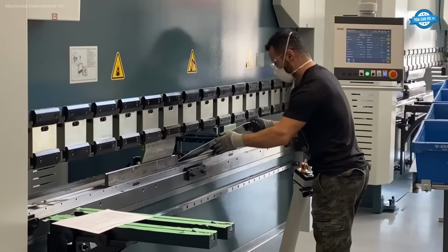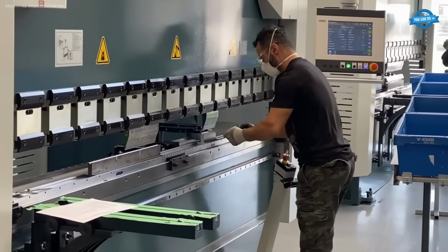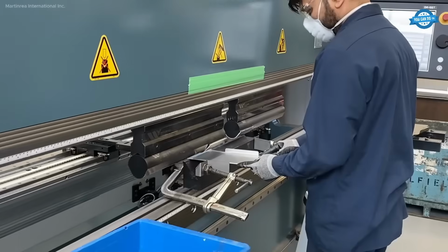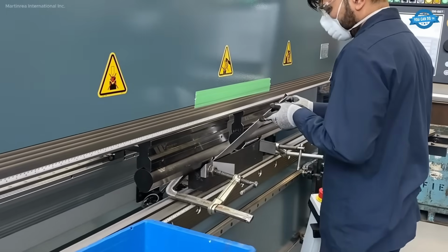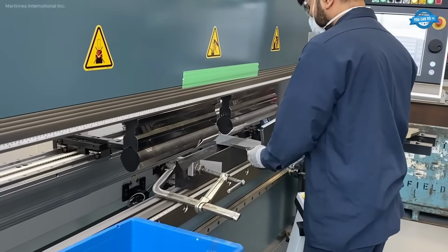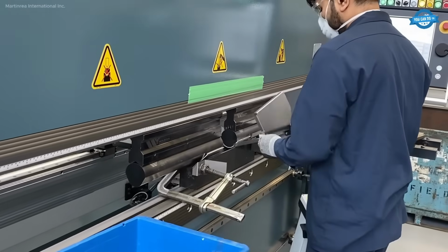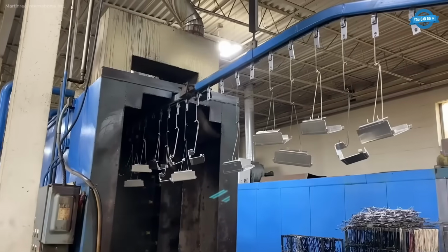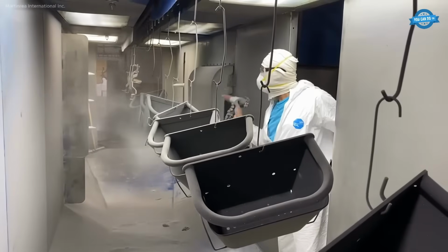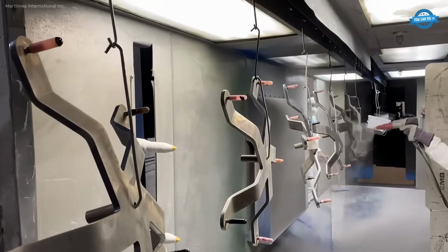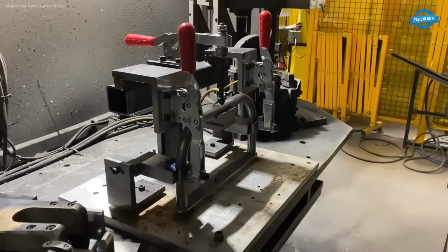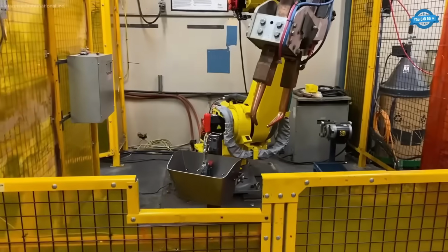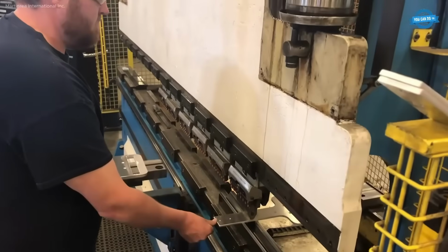Robotic GMAW cells with pulse spray transfer joined the assemblies, using fixturing adapted from seat frame welding nests to hold plus or minus 0.5 millimeters datum accuracy. Inline eddy current probes verified weld penetration on every part. A powder coat line running low-bake epoxy polyester cured at 160 degrees Celsius prevented temper loss.